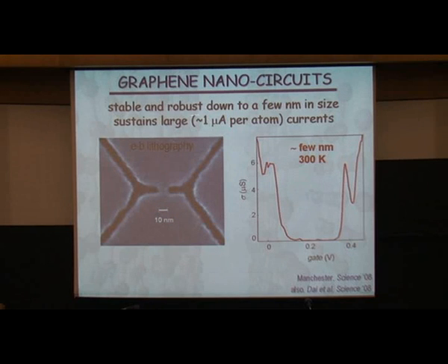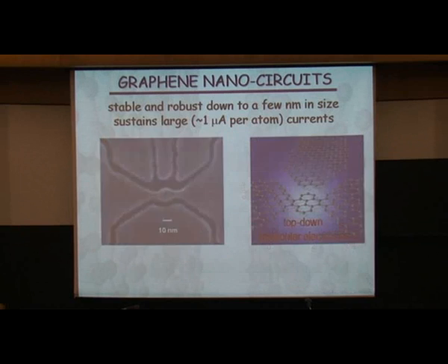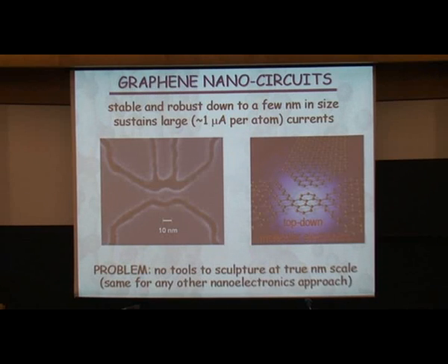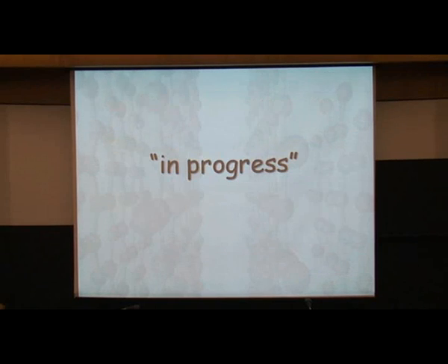But what is fascinating is that the current graphene sustains is about 1 microamp per atom. As I told you, copper or anything like that would immediately evaporate, and actually before you apply current would diffuse around. This material is fantastically stable. So the dream, which was and still is, to go by a top-down approach to molecular electronics. If we can come up with devices of such accuracy, we're in business, but it remains a dream, pushing many groups within the area.